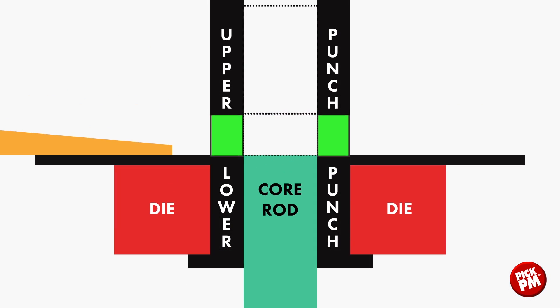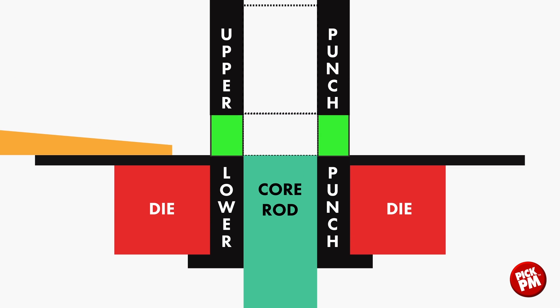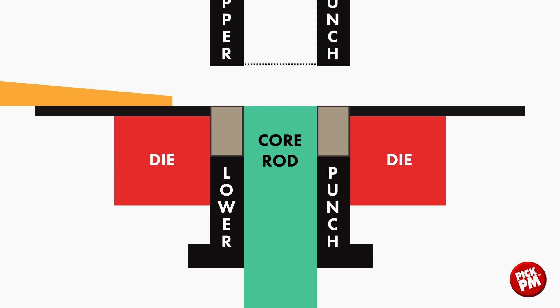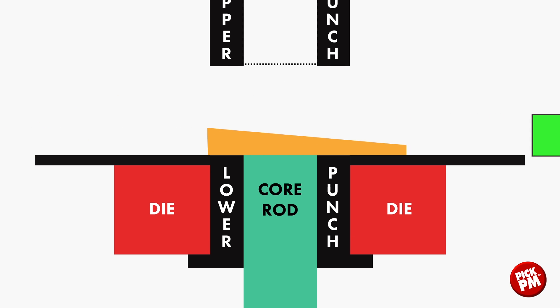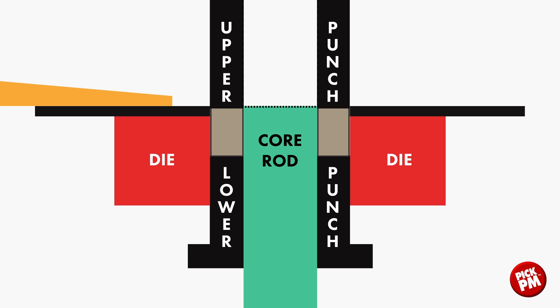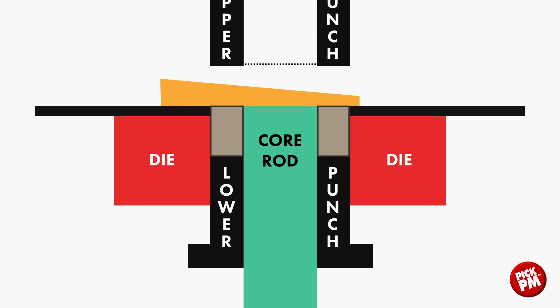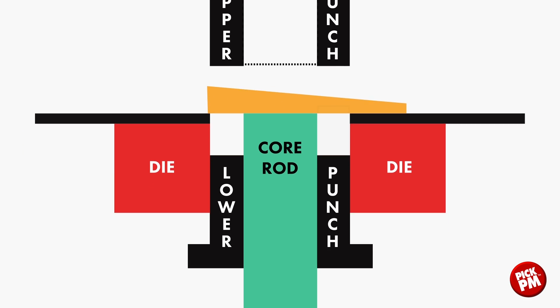In the compacting process, powder is carried over the die cavity with the feed chute. The upper punch closes off the die and forms the component in the closed die. We have an upper punch entering, a stationary lower punch, and the die in red which is movable. The upper punch closes off the die after filling the cavity, the lower punch remains stationary, and the die travels down. This process is known as withdrawal-type compaction.